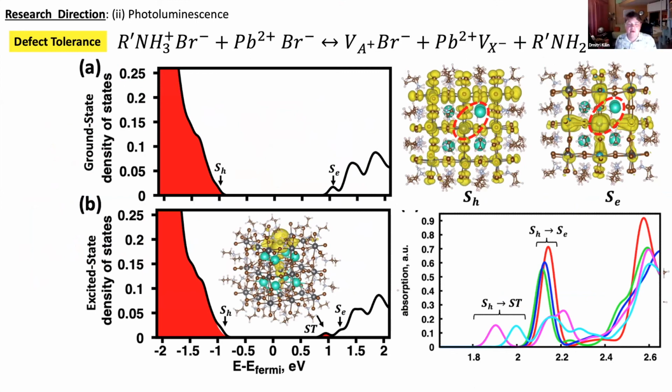Okay, so this is a transition from the valence band to a surface trap. If one tries to recompute with a different size of the nanocrystal, different type of ligands, different functionals, qualitatively this feature appears again and again. So I'm just showing one case, but it's a common feature. Okay, thank you very much.